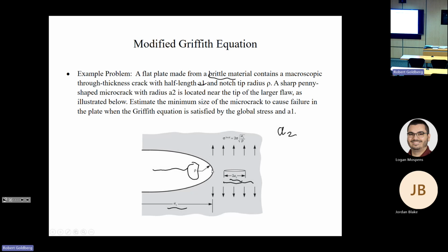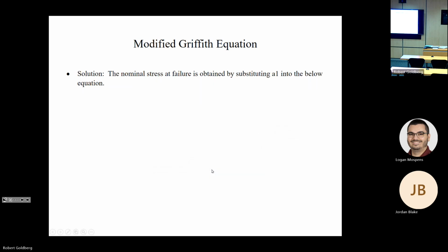And we'll be using just the Griffith criteria to solve for this. So what we have is that our nominal stress at failure for the big crack is, we have our failure stress is equal to 2 times modulus times our surface energy,